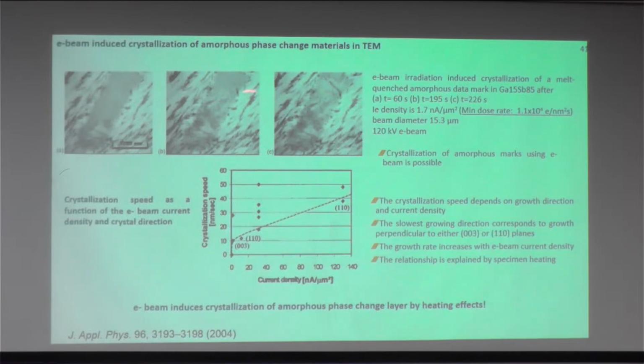After a time of 60 seconds to 200, 220 seconds, we can see that after some time these amorphous areas became crystalline.